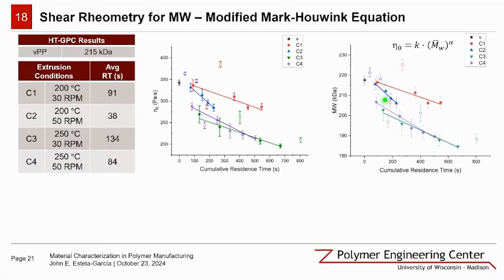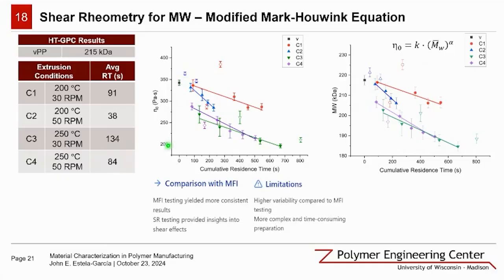So when we performed rheology, we had mentioned that we made these little discs. We compression molded these discs. We utilized cone and plate, steady shear, and oscillatory rheometry to capture changes in viscosity and shear effects. So these results were utilized to construct viscosity curves, but the data shown here is simply focusing on the zero shear viscosity captured from the Newtonian plateau.